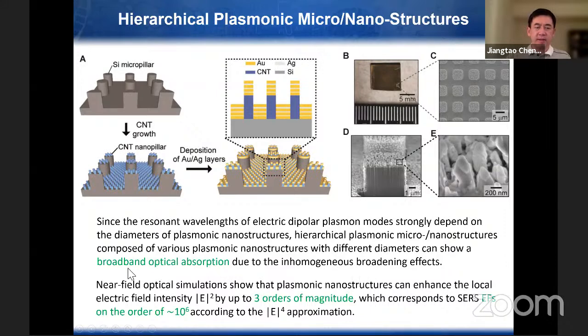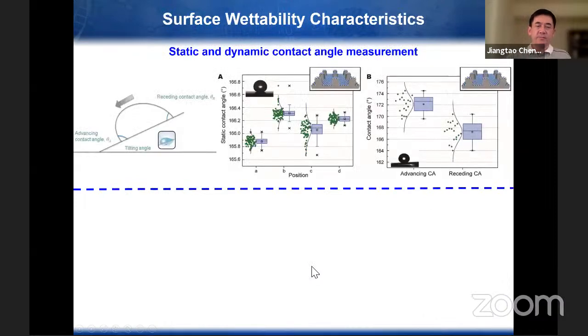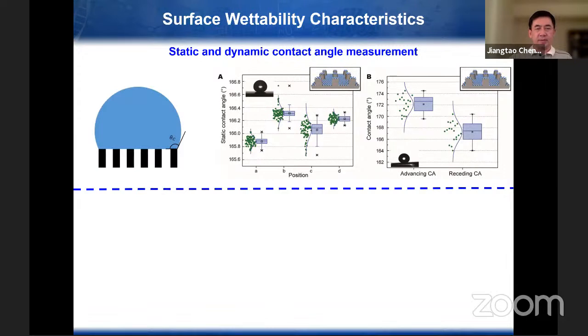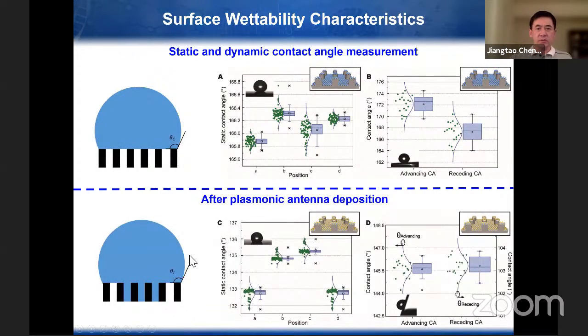So which means it can exhibit a broadband optical absorption. Now, droplets sitting on the roughness can stay in two states. One is the Cassie state, which means the droplet is only in contact with the tips of the roughness. And also, with the deposition of the metal layers, the metal itself is hydrophilic, so we can say the droplets can actually fill in the interstitial cavities. So this is the Wenzel state.